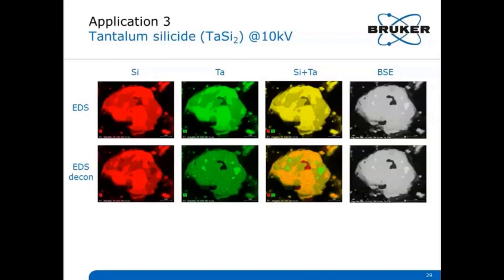EDS deconvolution results in a quite different picture for tantalum. You see here the differences. We see local enrichment matching the BSE image. So enrichment where we see the bright spot in BSE.